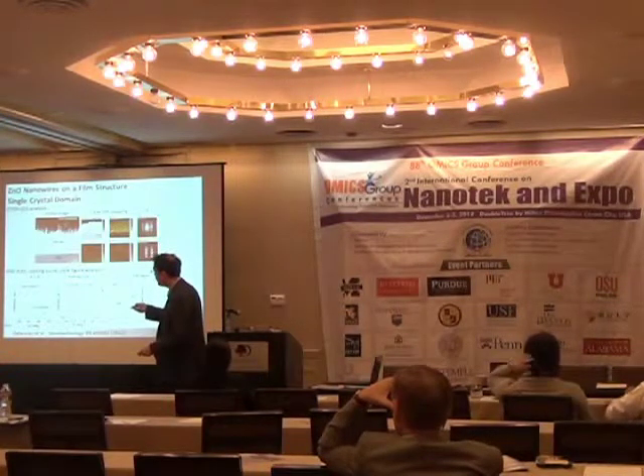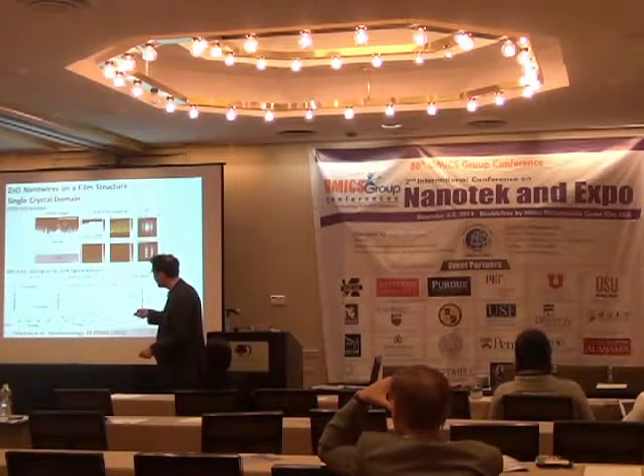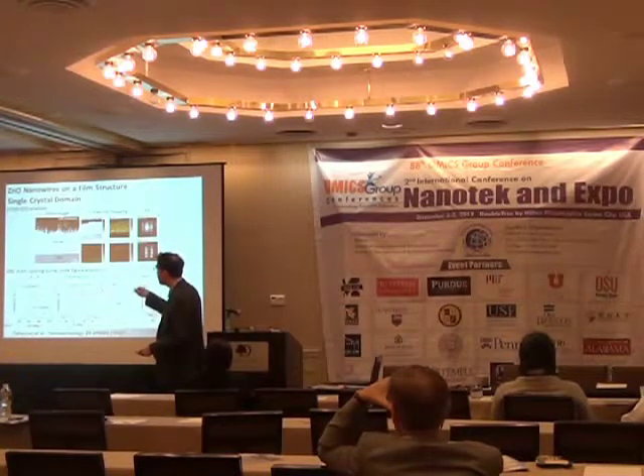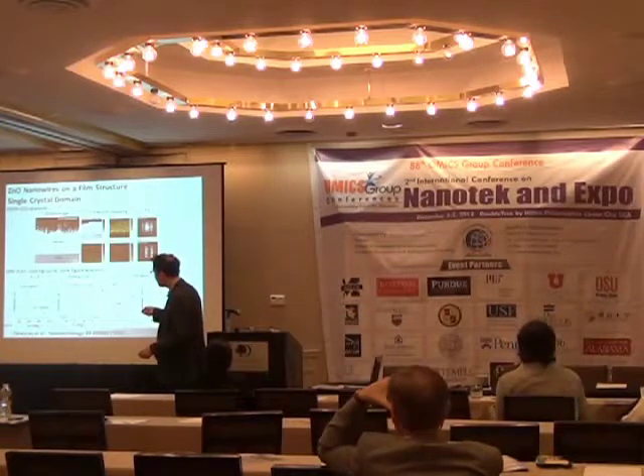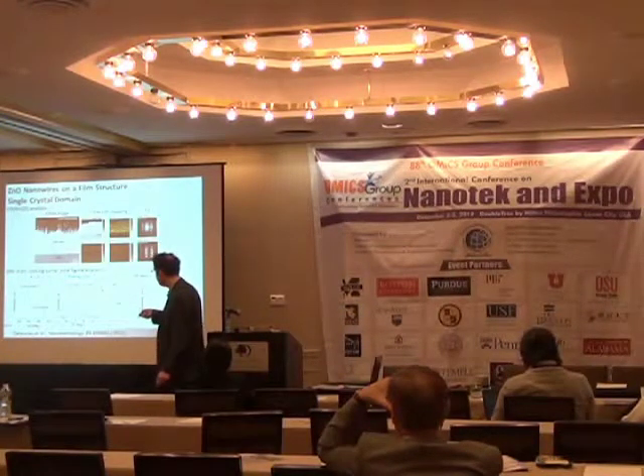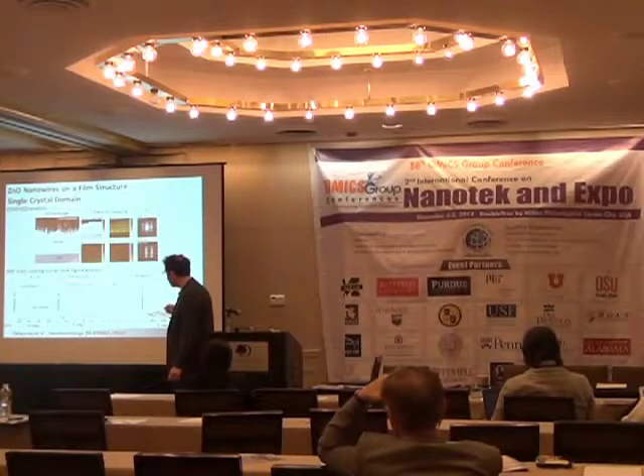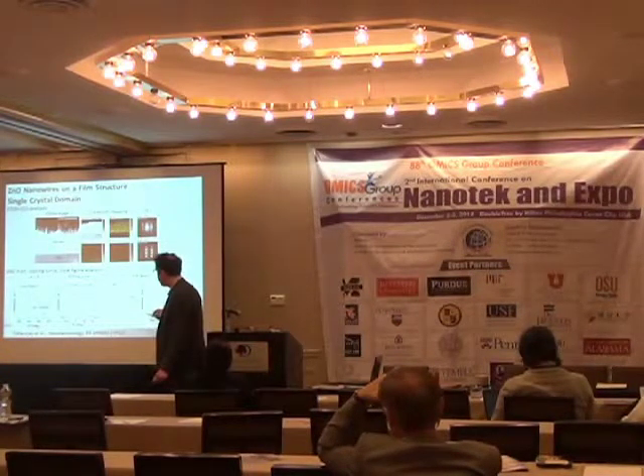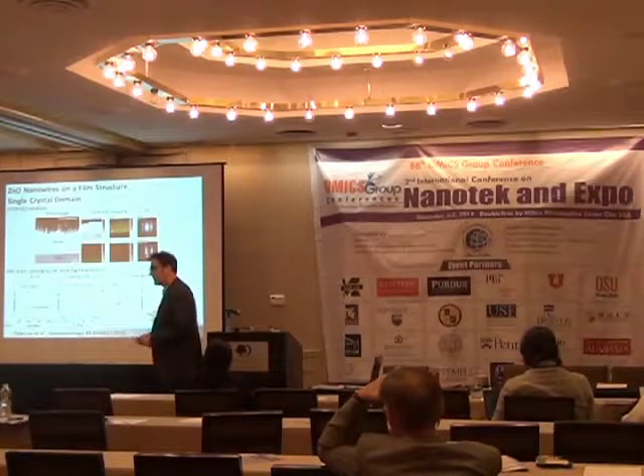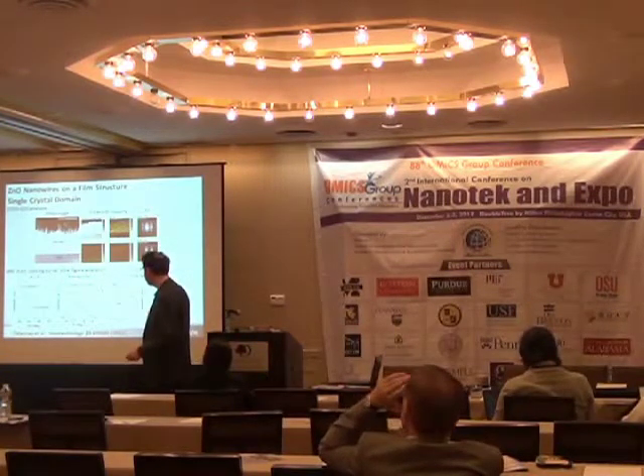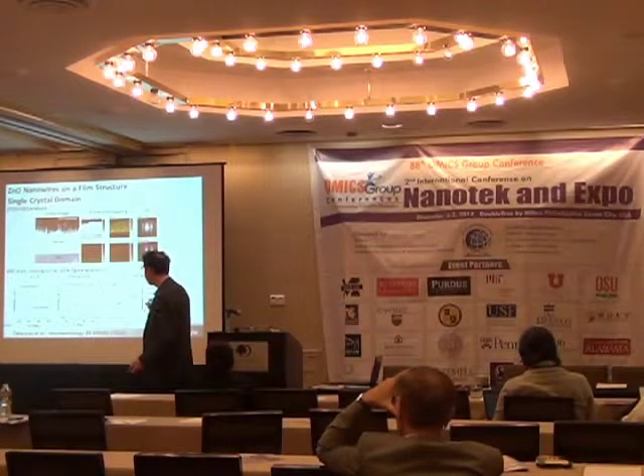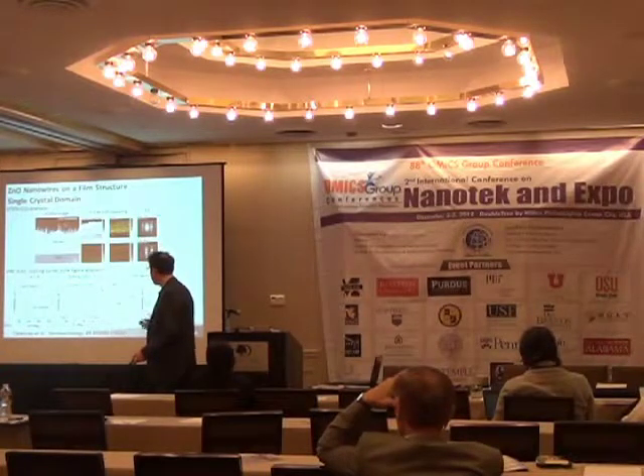So it means that both are aligned, and therefore they form a single crystal. On a larger scale, we also do X-ray diffraction and obtain only one family of peaks, 002. That means that the plane is aligned. And the rocking curve is extremely narrow, the width of the rocking curve is very narrow, so it's a good indication of a good crystal. And finally, you have the pole figure here, which has 6 dots, 1, 2, 3, 4, 5, 6, which is the typical pole figure of a hexagonal crystal. Hexagonal means you have a 6-fold rotation symmetry, and therefore 6 dots here. So that is a proof that the material is in the form of a single crystal over quite a large area.